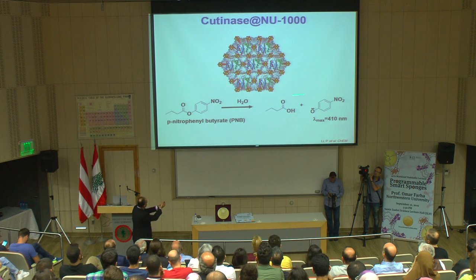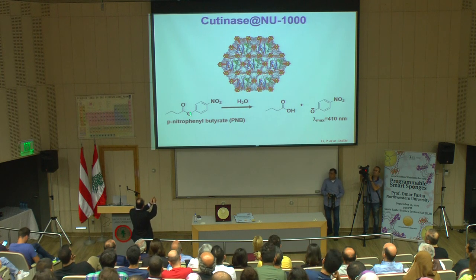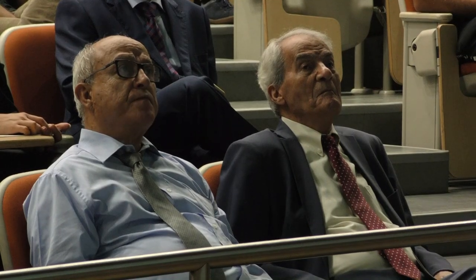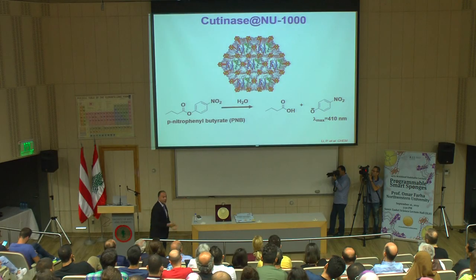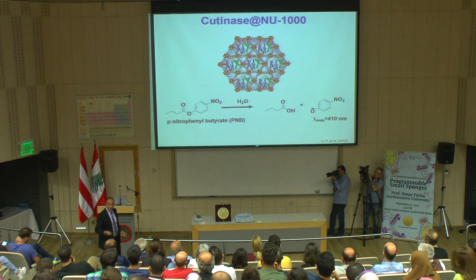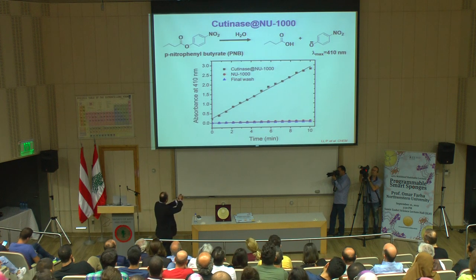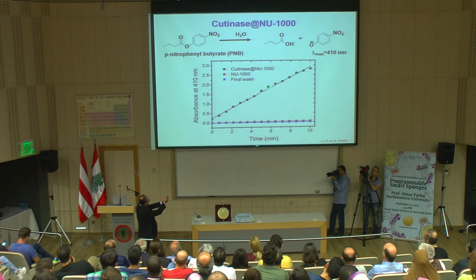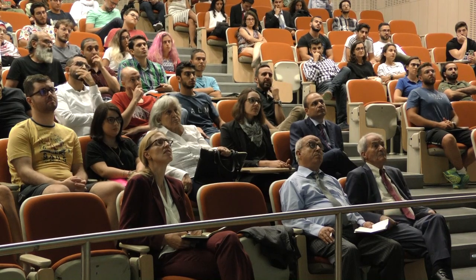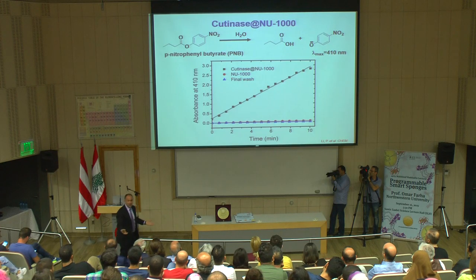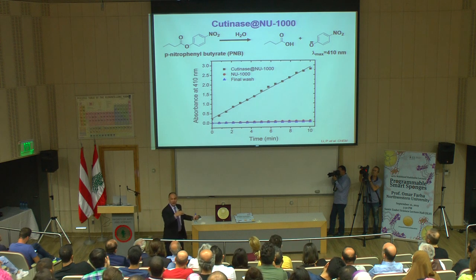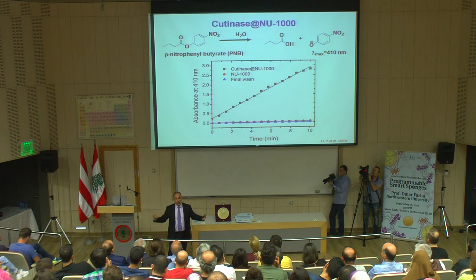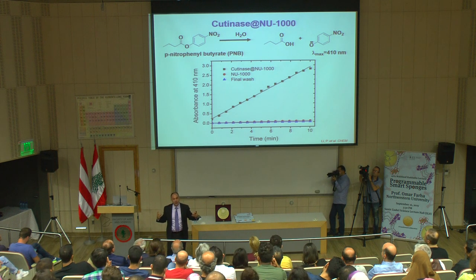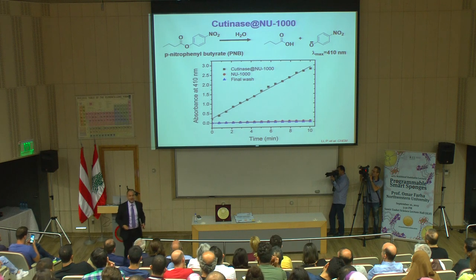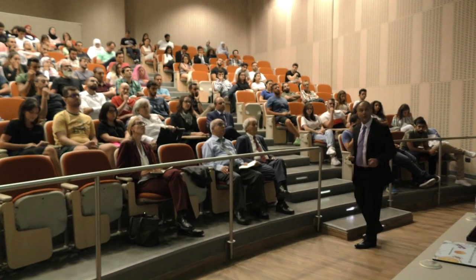This enzyme is a hydrolase, capable of taking this ester into this acid, and we monitor that, you know, the nitrophenol, using UV-Vis to see how much of that product we are making. So this enzyme is very efficient. It works quite well. So this is the adsorbent. Here is the MOF itself, so it doesn't do this reaction. We know the enzyme is doing this reaction. And when we filter our material out, you do the reaction and there is no reaction. That means we're not really leaching out the enzyme into the solution and doing a homogeneous catalysis. This is a real heterogeneous reaction from the composite.